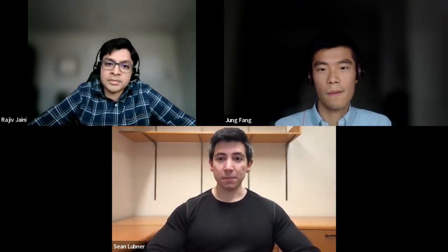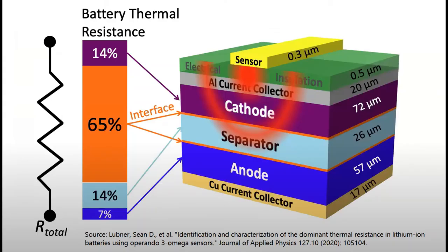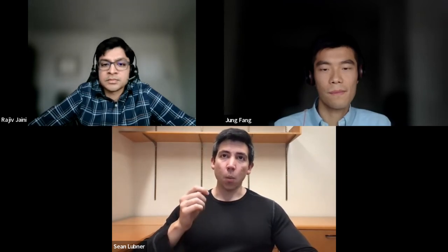And what we were able to see, because we had these non-invasive sensors that could look at the battery and sort of profile its thermal transport properties during operation, is that the heat was getting stuck in between the layers. You see, so it wasn't the layers themselves. The problem was the thermal contact resistance from one layer to the next, which is specifically something you cannot see if you're taking the battery apart and measuring each layer individually. And then we also did some theoretical modeling to understand, from a micro scale picture, why that thermal contact resistance is so bad.